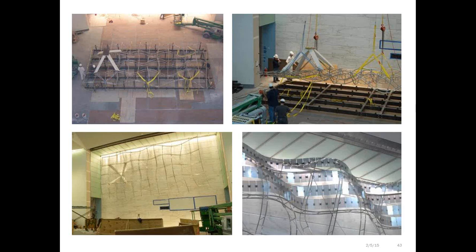The project itself had a fairly long design period where we got to work through materiality and design, and one of the things that became clear through a lot of design analysis is that the lighter the material is on the cantilevered section of the flag, the easier the unit was going to be to build and fabricate. So high strength, or higher strength than an austenitic, something higher than 30 KSI yield, fairly highly desirable. Unfortunately, the budget was limited, and so while we could have used an exotic, we couldn't afford to use an exotic. So in this case, 2101 represented for us a fairly good intermediate spot.